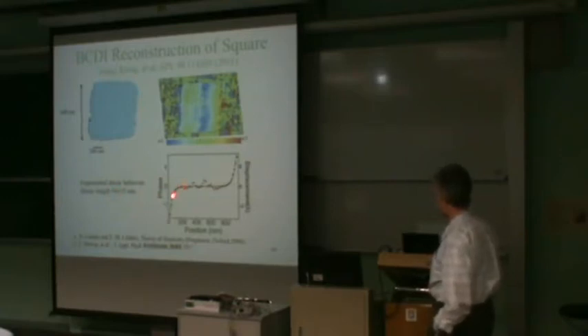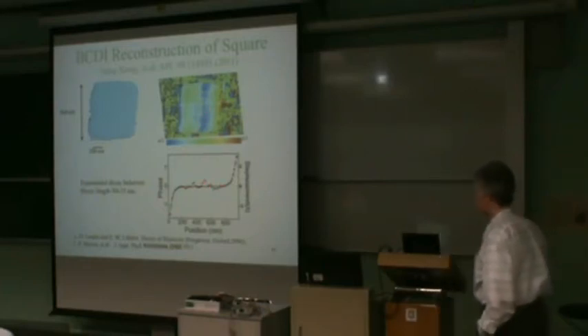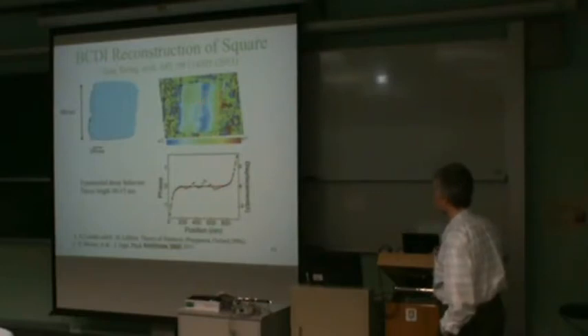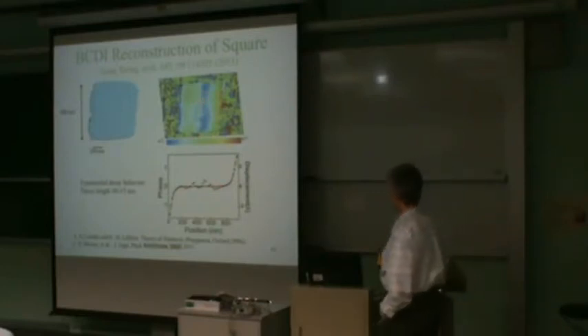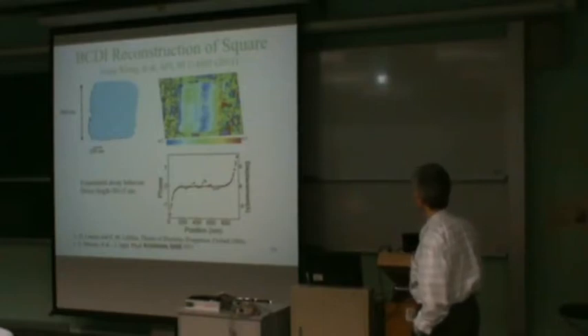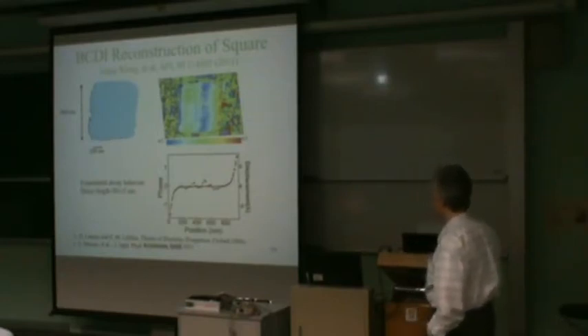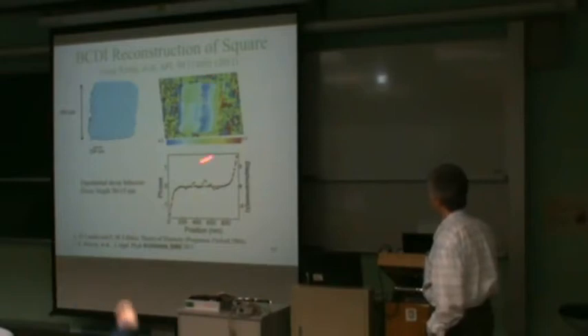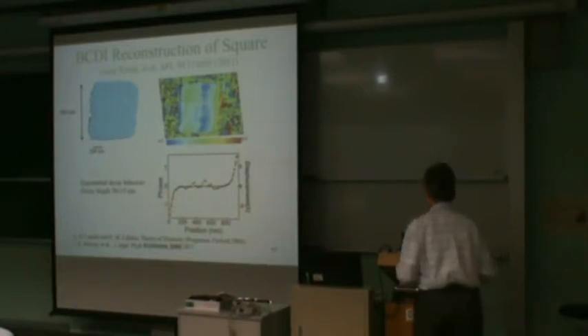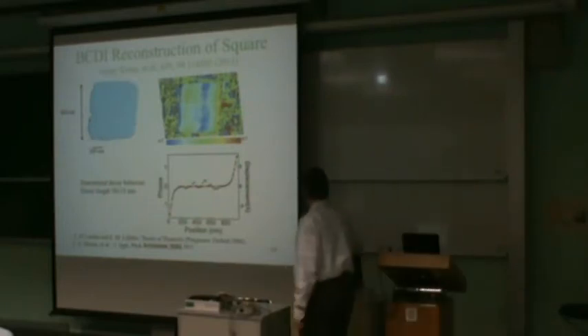So we've got a measure of the decay of the relaxation of the strain pattern at the edge of this slab, quite nicely measured. There's obviously some rippling going on inside the material as well, but that probably is imperfections of the strained silicon layer, which I'll say more about. Okay, so we've got pretty good agreement with the theory, but we went a little bit further and tried to model it.